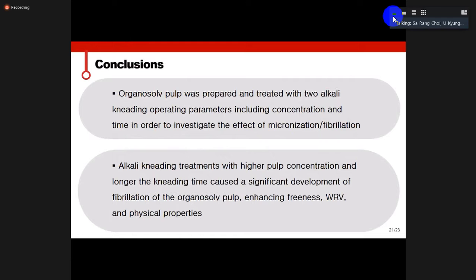This is my final slide. We carried out an alkali kneading treatment to fibrillate the lignin-rich organosolv pulp. And the effect of pulp concentration and kneading time on the micronization of fiber was compared. As a result, the alkali kneading fibrillated fibers well. Also, the higher pulp concentration and longer kneading time made a better micronization effect of the fibers.